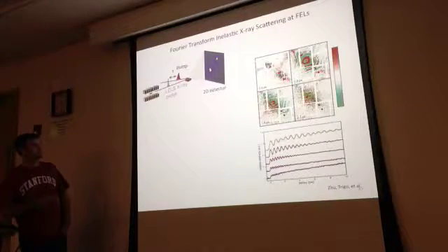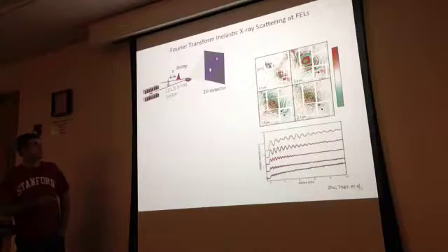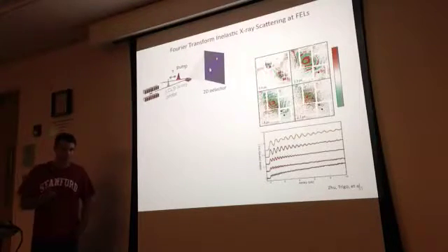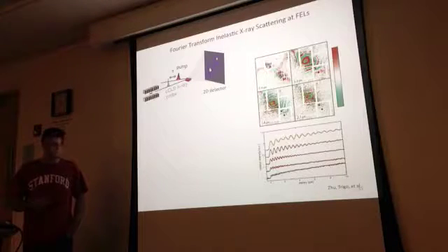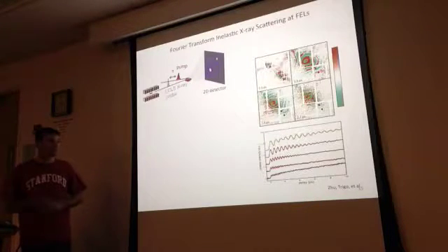This data was taken by Deling Zhu, Mariano Trigo, and myself at XPP and LCLS. And the way we did it was we used a short 800 nanometer pump pulse to excite the phonons in the material, and then used the short LCLS probe to take a snapshot diffraction picture. And what we did is we set the time delay between these two pulses, and then collected, like, say, 1,000 shots, and then averaged those, and then that's one frame of the movie. And then we changed tau a little bit, collected another 1,000 shots, averaged, and then that's another frame in the movie.